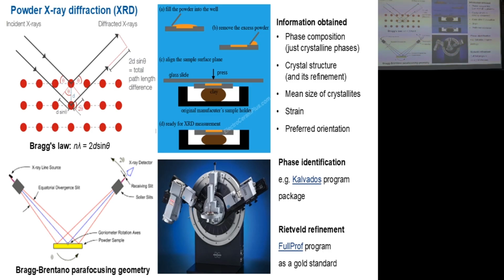Importantly, you can also analyze the size of crystallites, because there are some effects that affect the width of diffraction lines and that are related to the size of particles. Also, you can analyze some strain effects, maybe some compressive strain or some general strain related, for example, to some chemical heterogeneity in your solid solution. And you will also see effects of preferred orientations.